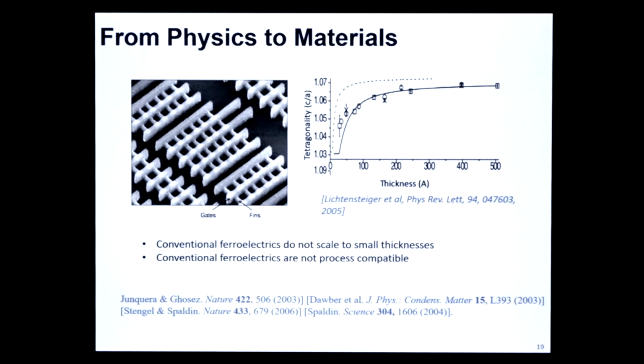The other thing, which is more fundamental, at least that's how it looked at that time, is that in the 100 years history of perovskite ferroelectricity, we know that when we reduce the thickness of the perovskites, due to the size effect, due to the depolarization field that comes in, perovskites become very weak in ferroelectricity, and for most perovskites, the ferroelectricity goes away below 5 nanometers. On the other hand, if you look at our advanced devices, even in 2018, the FinFETs, the fin pitch, the distance between two fins, was only 43 nanometers. Today, it is only 29 nanometers.